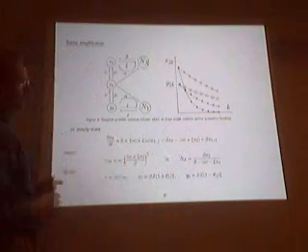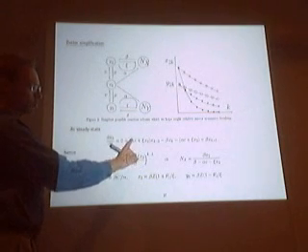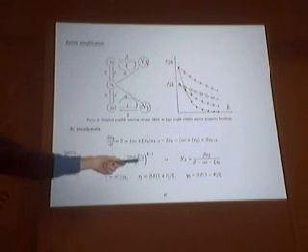The clusters of size k plus 2 can fragment at this rate beta, so these are size k, and they aggregate at a rate that depends on the dimers of type X and the amorphous dimers. So if you assume that this is close to steady state, you could solve this to find out something about the size distribution, and you find that the size distribution decays exponentially.